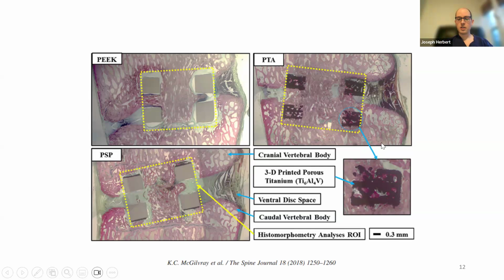And so unlike the PEEK graft, this graft has been modified on a structural level to help with its biological activity. And just anecdotally, porous titanium can be either 3D printed or machined to varying degrees of porosity, depending on the particular strength characteristics you're going for. But I've actually heard, again anecdotally, of a spine surgeon who used a porous titanium corpectomy cage, and for whatever reason, and this is still not totally understood, this porosity on a nanoscale of titanium is extremely biologically active, and so it not only induces bone growth, but in this particular patient, it actually grew through the patient's esophagus. And they had to go in and do it. It's just kind of a whole disaster.